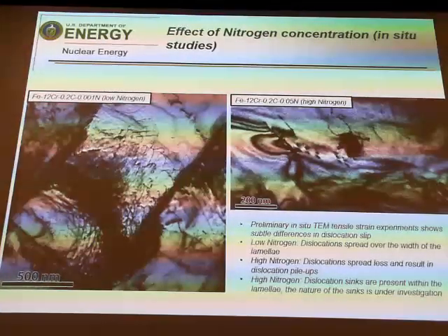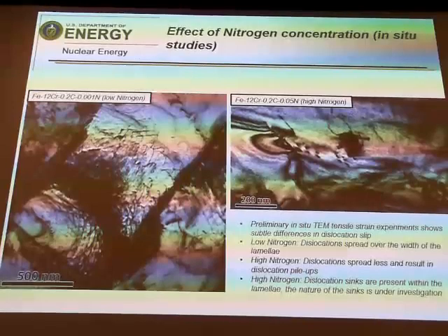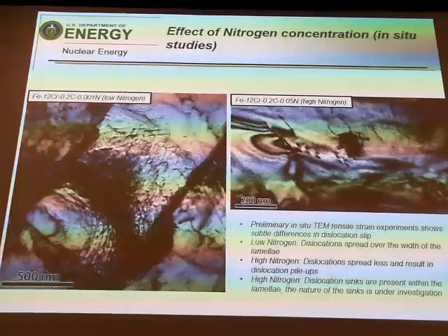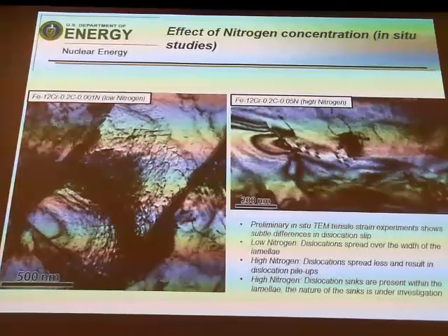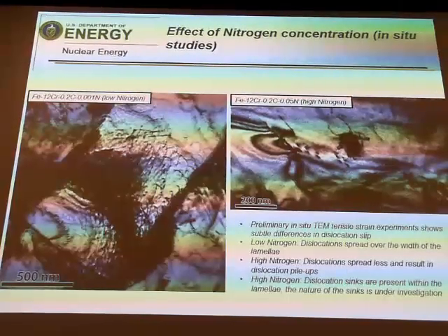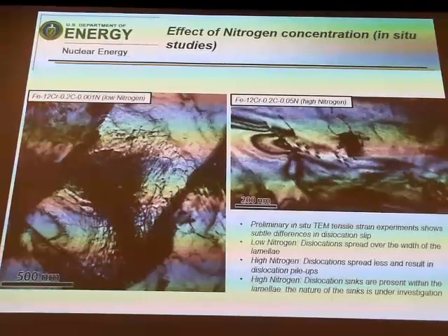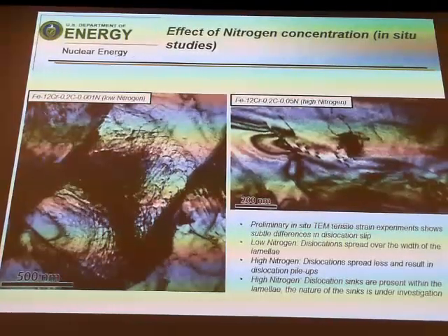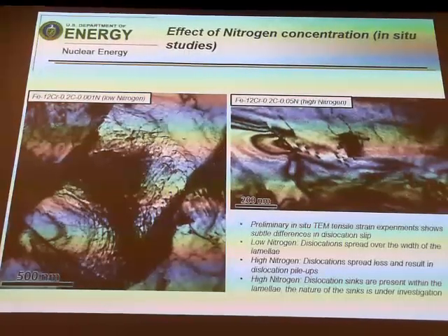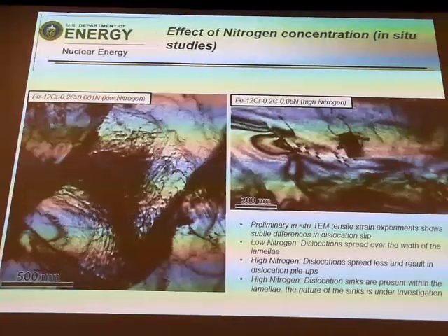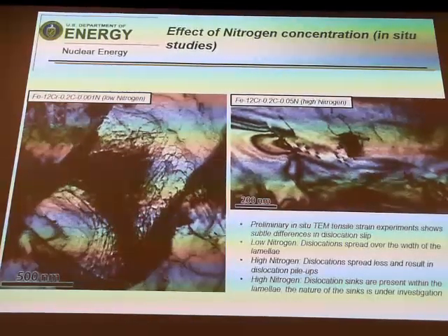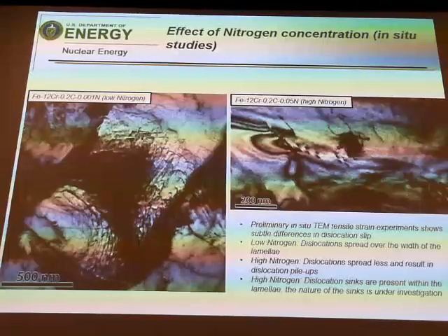And hopefully this will work, but we're starting to do some in situ straining studies on the material. This is the low nitrogen alloy, just looking sort of down the lath, and you can actually see fairly uniform movement of dislocations, actually down the lath, across this, from one side of the lath to the other.